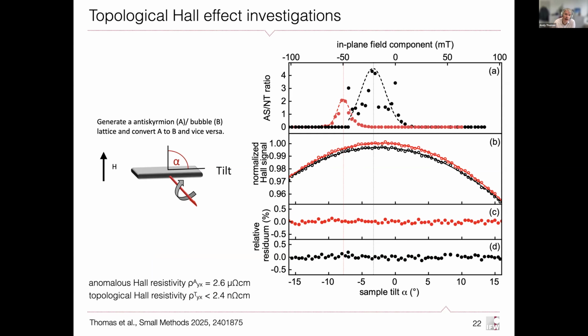So this is now the ratio between antiskyrmions and non-topological bubbles. And you see it goes up to 4, which means at the extreme case, at one particular angle where we have the most antiskyrmions, we have 4 times as many antiskyrmions as non-topological bubbles. So it's like 80-20. And on the way back, we don't quite reach that. We have 2, but nevertheless, we have these distinct angles of, let's say, -3.5 and -7 or 8 degrees, where we have the most antiskyrmions.